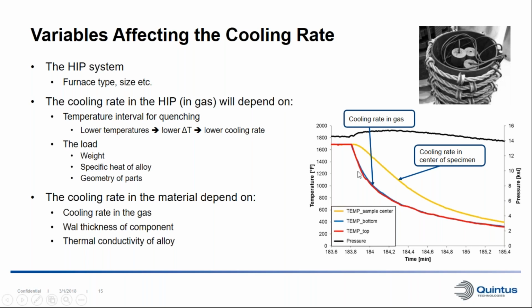So if we look at the right here, we have a cooling curve from a HIP cycle, and we can see that the cooling rate is higher here at higher temperatures than down here at the lower temperatures. The load that we're processing also has a big effect on the cooling rate. And the load in HIP language is the parts that we're treating and also the load basket. So kind of the thermal mass that the furnace has to process. So the weight of the load is quite important, how much material we're going to cool down.